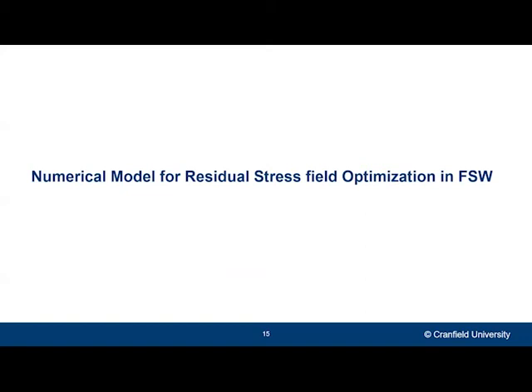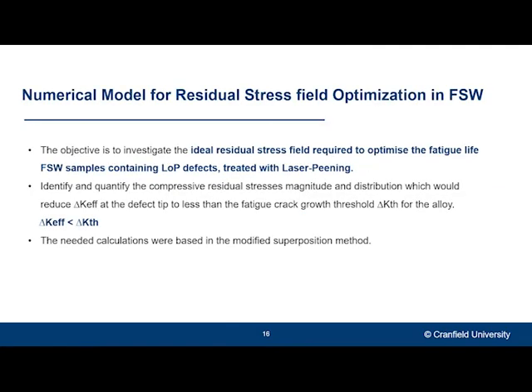Instead, I'm going to show you some other research strands that I have also been working on for this project, which consists in developing an FE model to try to optimize the residual stress fields in friction stir welding. Essentially, I am investigating what is the ideal residual stress profile that I need to achieve with the laser peening in order to optimize the fatigue life of friction stir welded samples containing lack of penetration defects. I'm doing that by calculating the delta K effective at the defect tip and comparing that to the delta K threshold. The assumption here is that if the delta K effective is smaller than the delta K threshold for this alloy, then there will be no crack initiation, presumably.